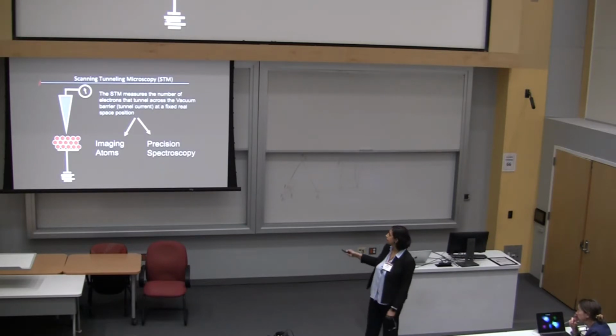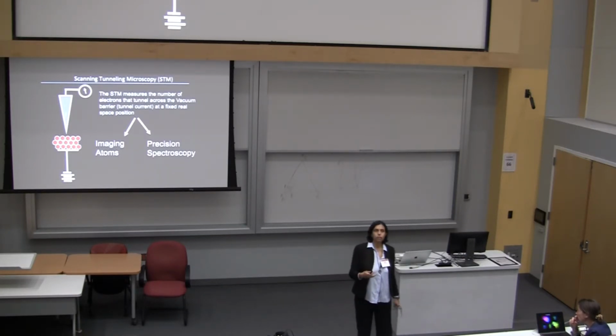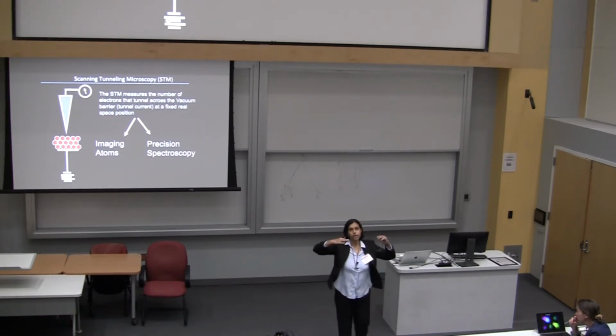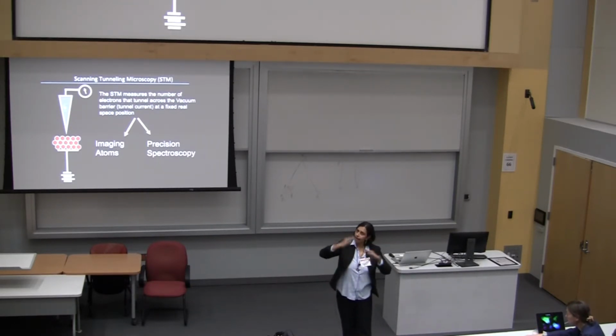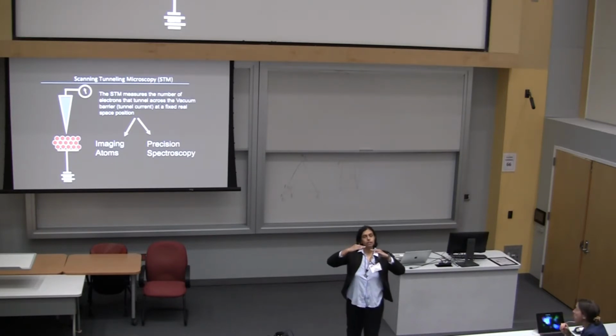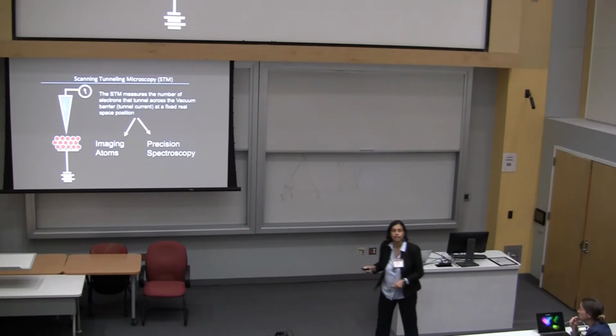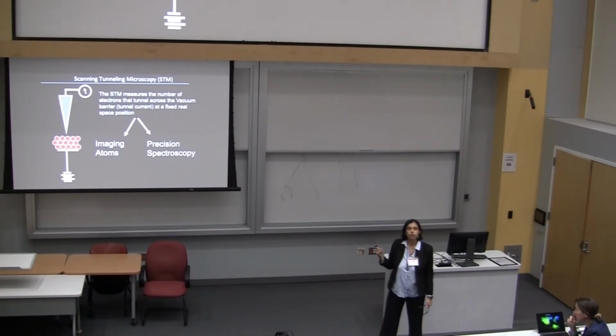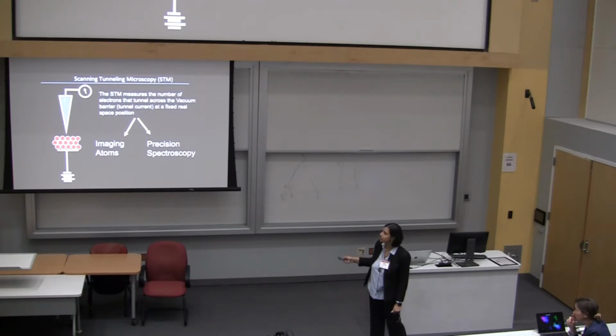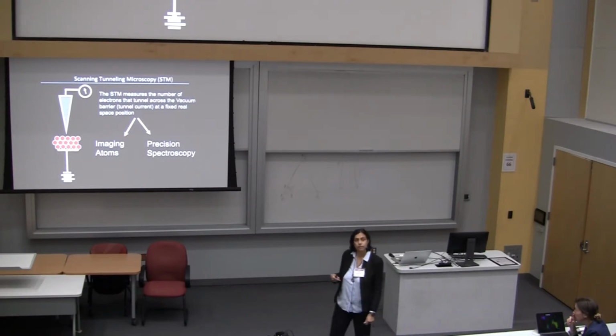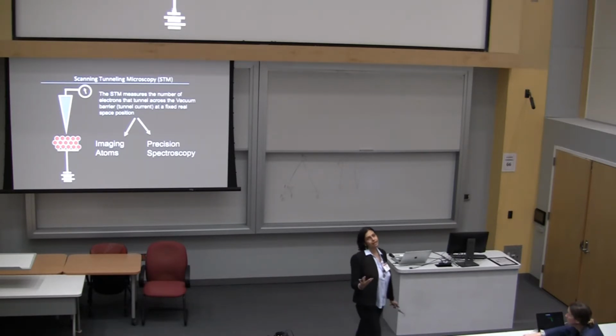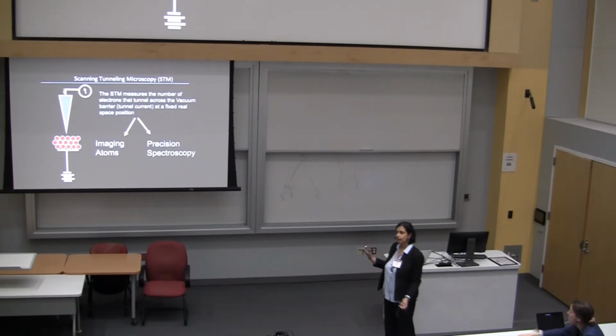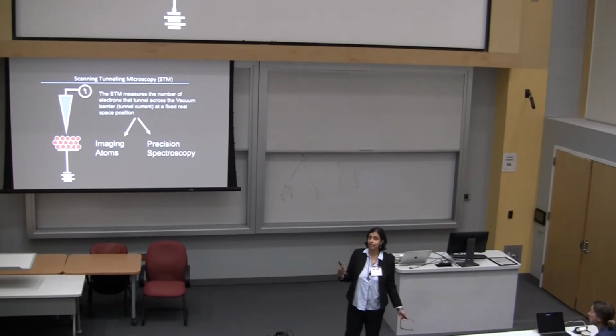What we can control is the bias voltage. In fact, zero bias voltage is the Fermi energy, when the Fermi energy of the tip and the sample line up. Anything we do with the bias voltage moves the Fermi energy of one with respect to the other. I'll show you that in a second. We can also control temperature. We can control the height between the tip and the sample using piezoelectrics. We can turn on a magnetic field. We can make the tip magnetic. You might think of doing exotic things in the future, like turning on light and seeing what happens, but there's not a lot done in that direction yet.